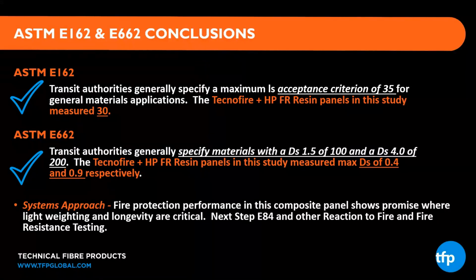We've also concluded that the systems approach, fire protection performance in this composite panel shows promise where lightweighting and longevity were critical. Adding multiple components is really the way to go. When you look at some of these harder tests, like an E119, an NFPA 285 or 286 test, the next step would be to just really run the E84, which is another flame spread and smoke test, and then look at other reaction to fire and fire resistance testing. Next slide, please, Neil.